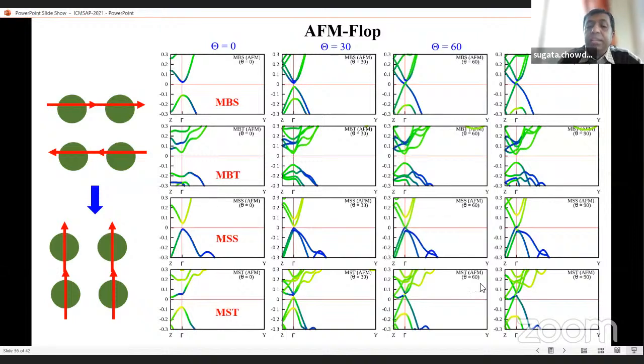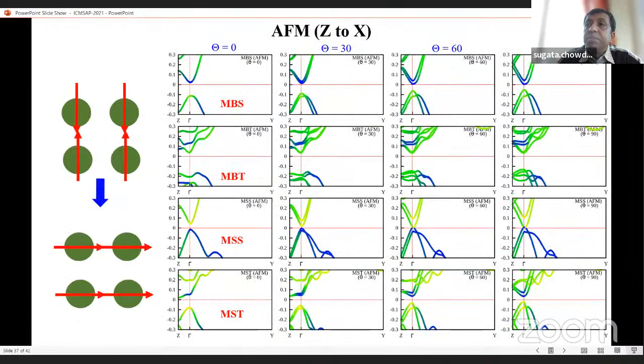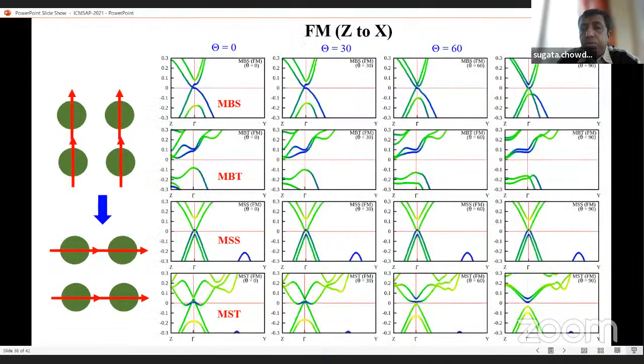On the other hand, the MST, the manganese antimony telluride system, is showing a Weyl semi-metal phase. Then the second thing is what happened when the antiferromagnetic order goes from out of plane to in plane. We got a similar result in these cases, and we found that the manganese antimony selenide structure is a Weyl node. That tells us that manganese bismuth selenide and manganese antimony selenide are showing a similar kind of robust Weyl semi-metallic node.